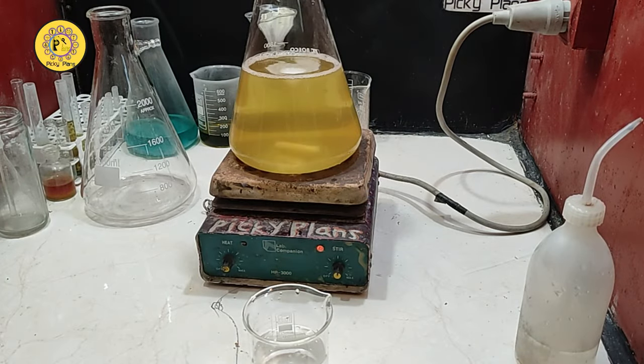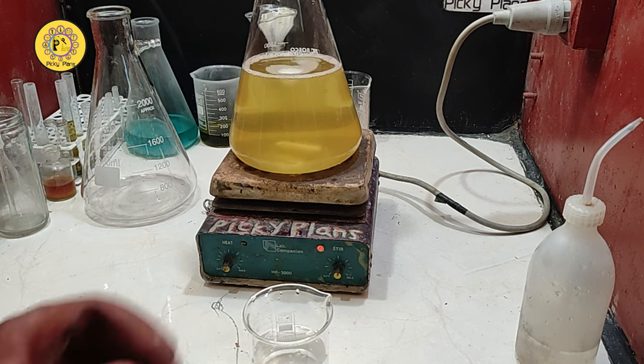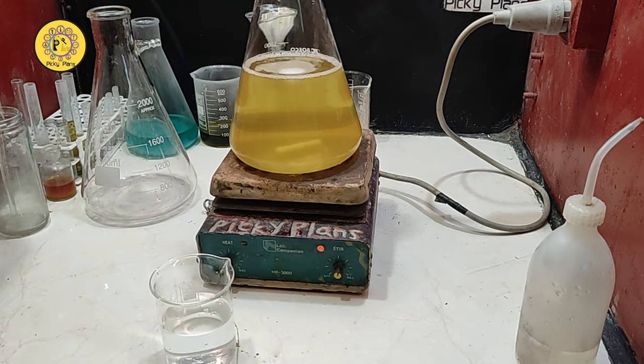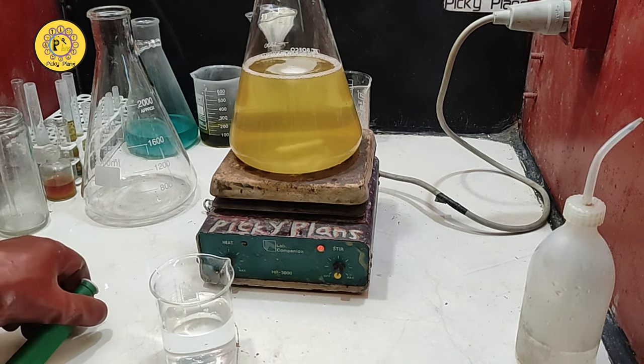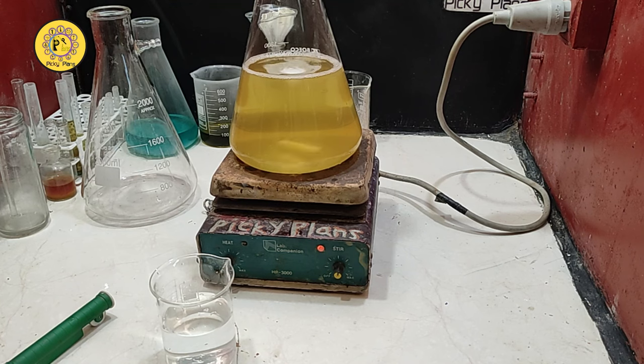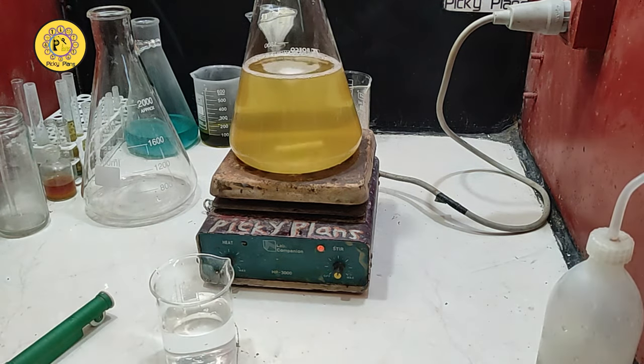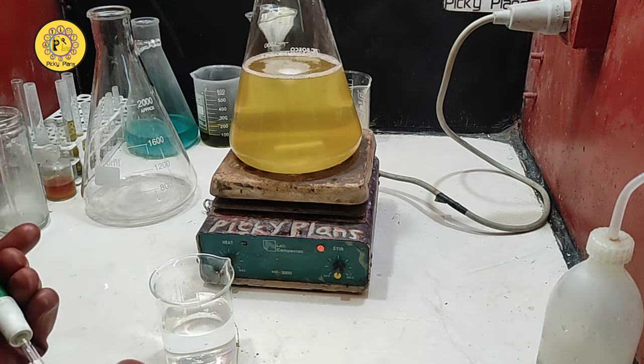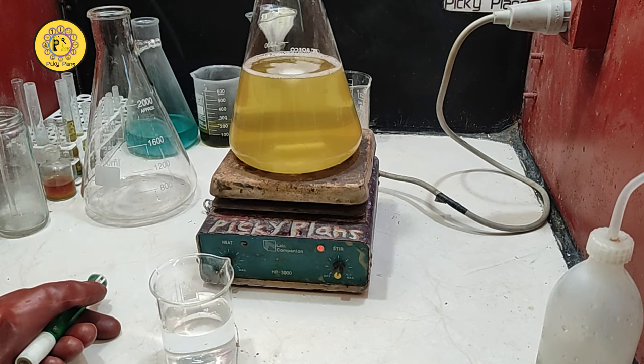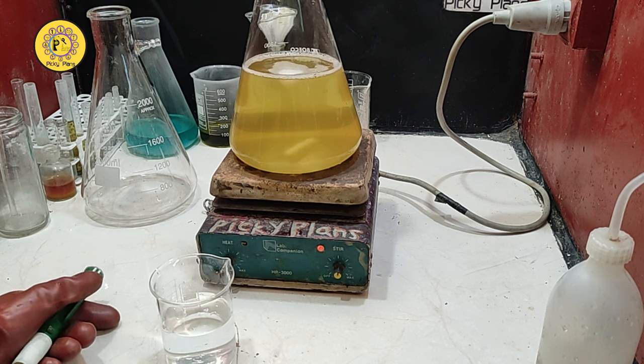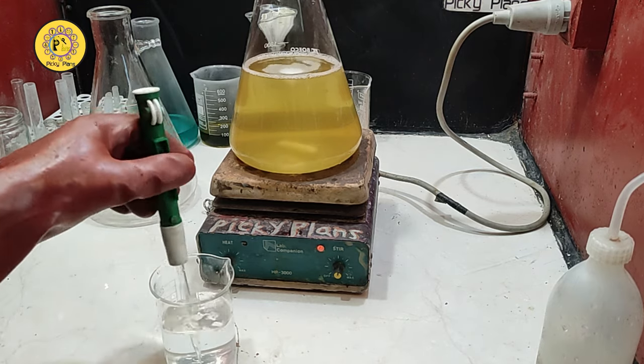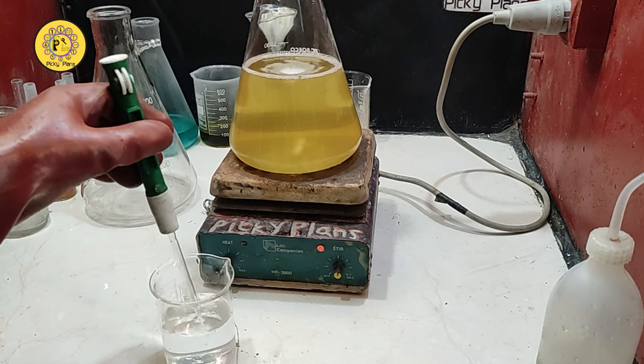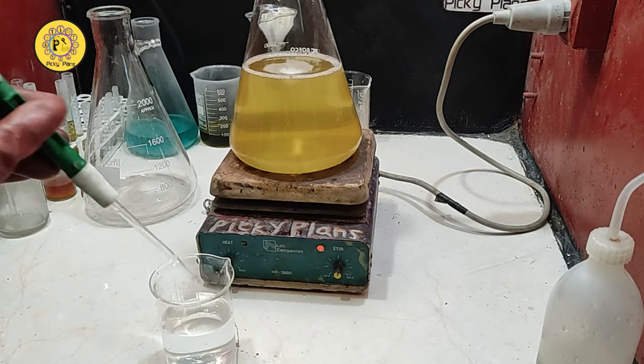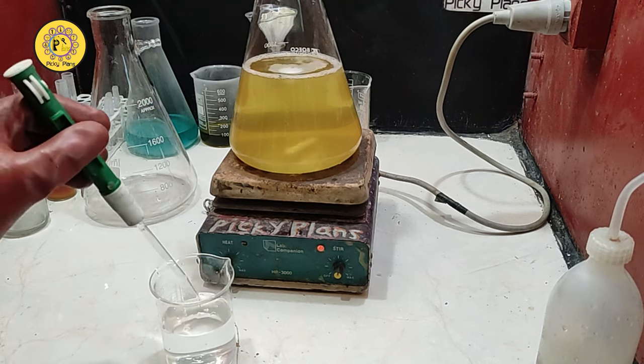To start cementation on zinc, I need to first acidify the solution. I do the cementation in two stages. The first one in a little bit acidic medium, and the second one is done in alkaline solution. So to get the sweet spot for pH, I'm going to add some dilute hydrochloric acid, maybe somewhere between 5 to 10%. 10% is way too much.